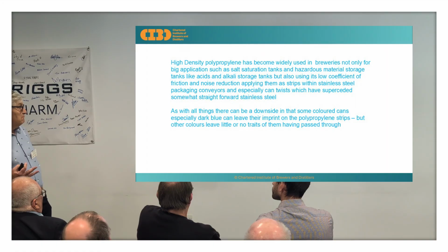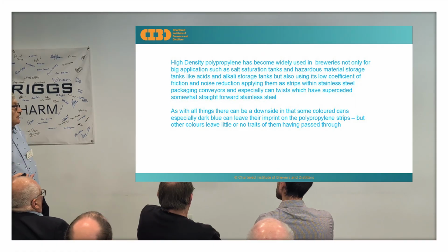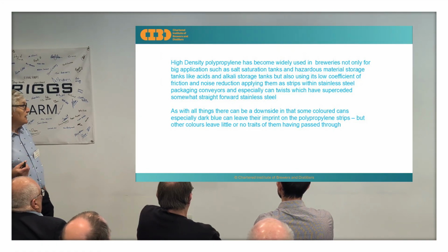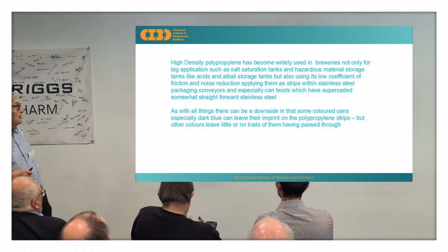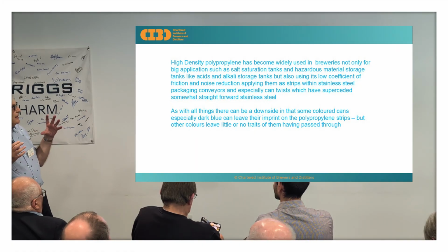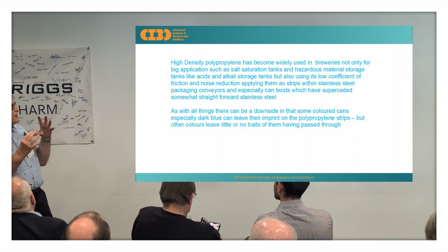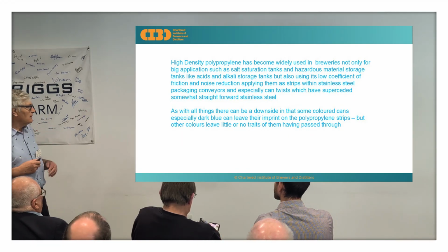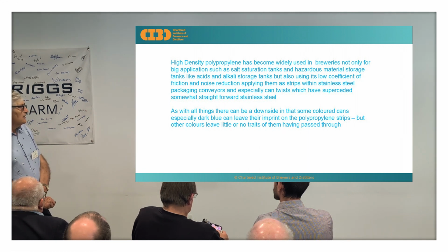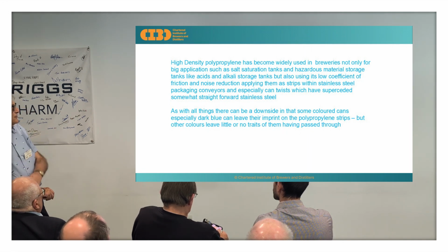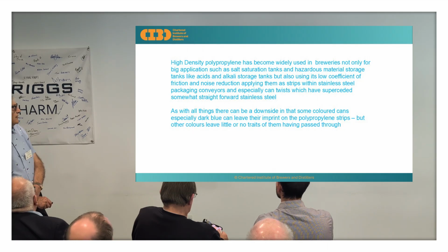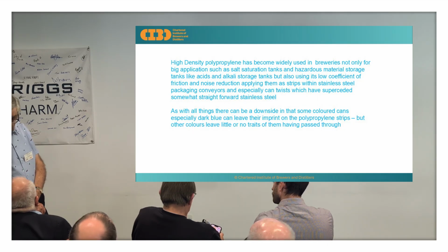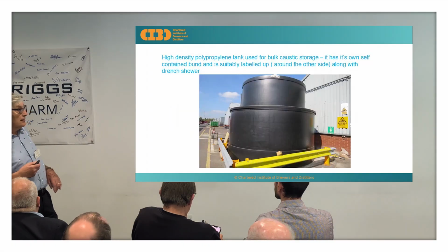But as with all things, there can be a downside, and that is that in some coloured cans, especially dark blue, they can leave their imprint on the polypropylene strips. It's almost like the ink that was used never dries onto the lacquer, and so you can get strip stains and you lose some of the intensity of the colour. But other colours are fine. 5 minutes. 5 minutes. Oh right. Okay.